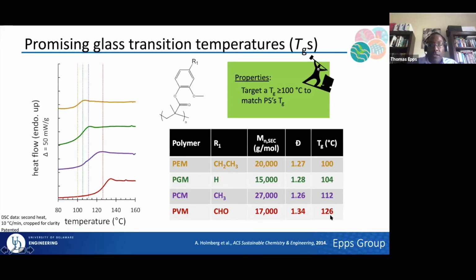So the key thing is that all of these materials as homopolymers have glass transition temperatures near or above 100 degrees Celsius. So this is quite nice because not only do they match polystyrene, but now you can imagine if I take this material here, PCM, so polycreosol methacrylate, if I were to make my quote unquote styrofoam-like cup out of that material, I could even think about boiling my water now in my cup as opposed to boiling it in a tea kettle and then transferring it over. So there's a lot of application where being able to get just above 100 degrees Celsius in glass transition temperature is quite useful.